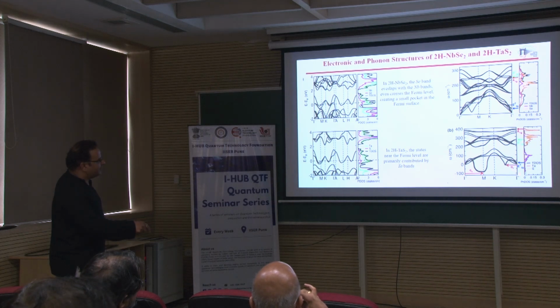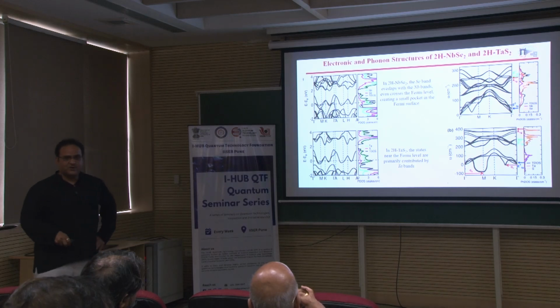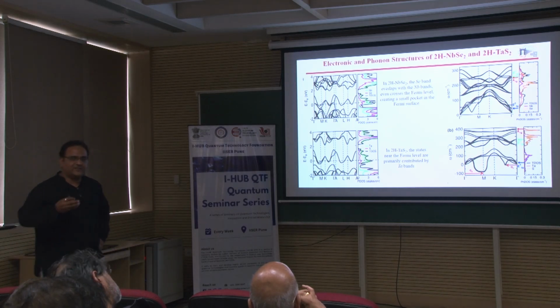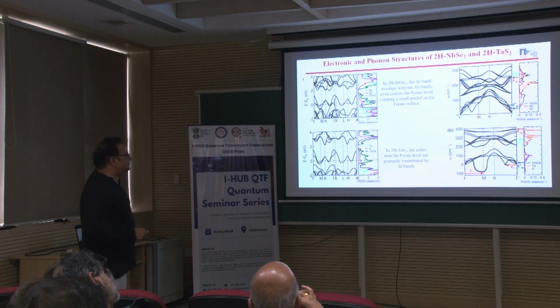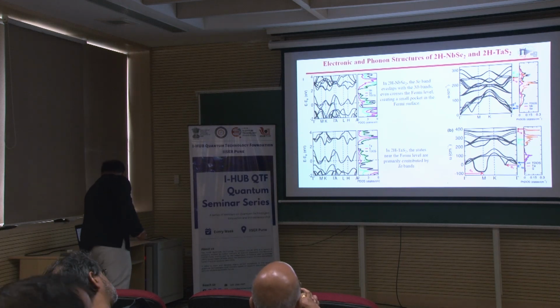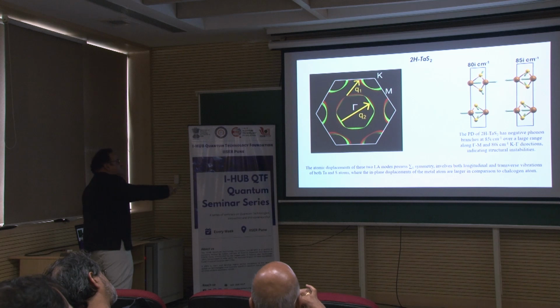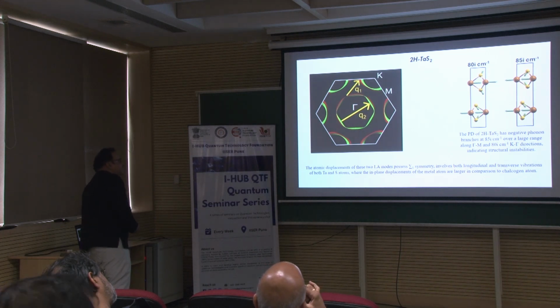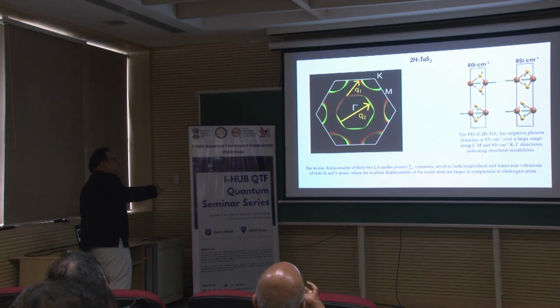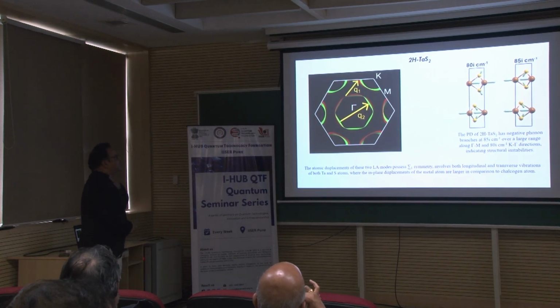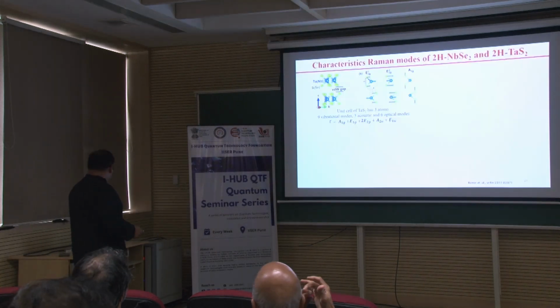One is from gamma to K and another one is gamma to M. So you have 2 new vectors, and there is an instability here because the frequency is negative. So the instabilities in tantalum sulfide can occur at higher temperature as well. All right. So this is the tantalum sulfide. There is a Fermi surface, and there are vectors related to the Fermi surface nesting here, but there is involvement of the electron phonon coupling as well.